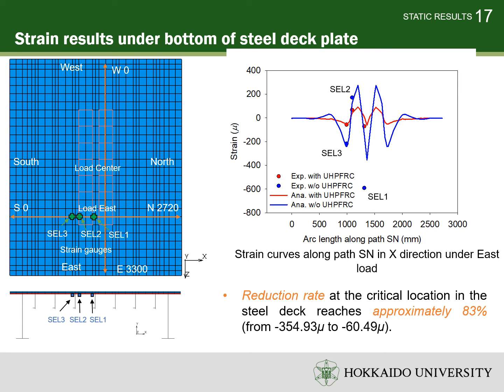The second reason is that the contact region of the rubber tires used in the models is not exactly the same as the real contact area in the experiment. From these figures, it is obvious that the strain level and strain range in the steel deck model reduced with the existence of the UHPFRC overlay. The strain reduction rates in the steel deck at the critical location at the middle of the SN line reached approximately 83% from the analytical models applying the strengthening overlay.